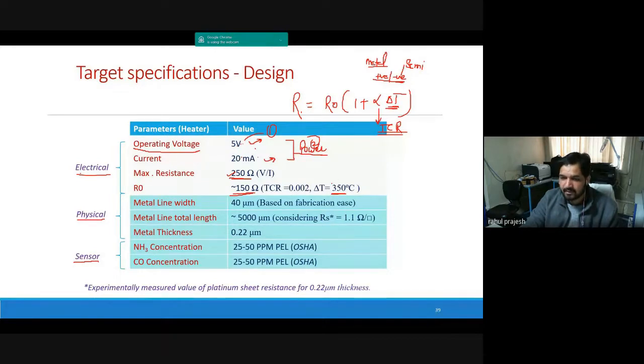For gas sensing application, a 300 to 350 degree centigrade change is good enough. Sometimes it goes to 400 degrees centigrade, but I'm taking an average case where this temperature is important in most cases. Based on this delta T, and since you know your material, this alpha is fixed for that material, and you know the maximum value R max, which we just calculated, so you can calculate the R naught. Now you know the initial resistance of your micro heater.